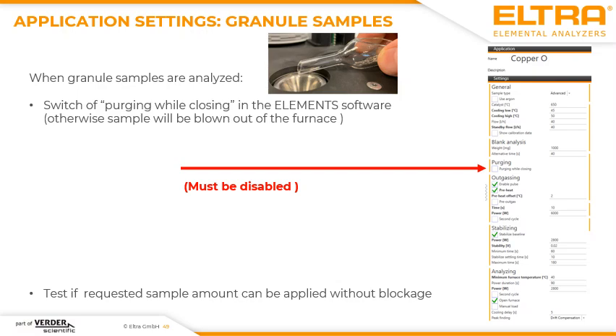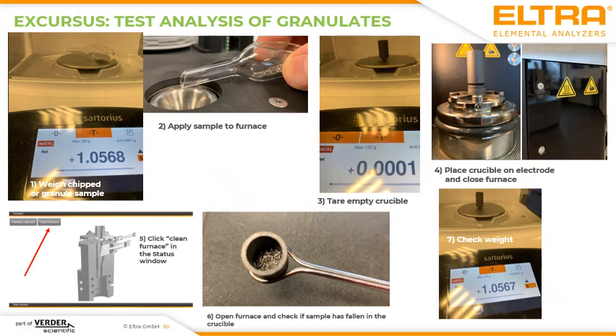When you would like to test the sample amount which is applicable to the furnace, I would recommend the following test procedure for your sample. This test procedure could be suitable when you run granule samples for the first time, or when the sample preparation is now done in a different sample shape, and you are completely unsure if all the applied sample will fall into the crucible and which sample weight is suitable for this application. So the following procedure could be suitable.